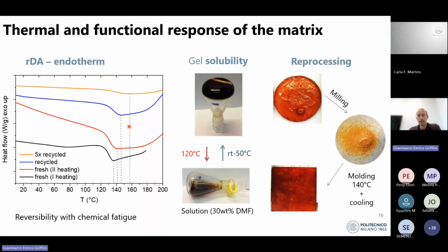Then we also checked macroscopically the reprocessability of the systems by solubility tests, and you see that by heating up the system in a good solvent for the precursors, we have full solubility of the material, and then if you cool down, we have a full gelification of the material, meaning that the reversibility of the adduct is actually verified. And we also reprocessed the system by heating up in a hot press, and we could consolidate the material and obtain again a fully cross-linked system.